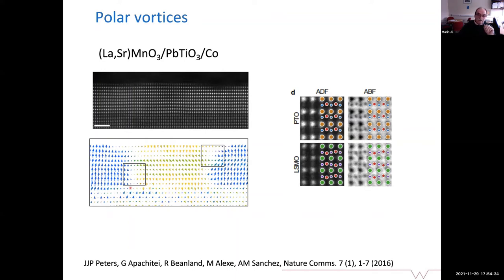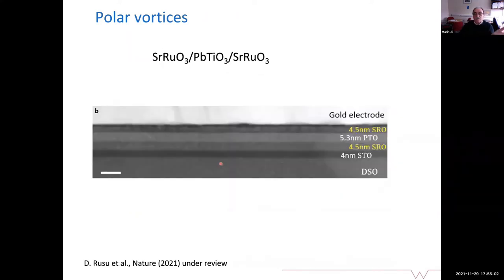But this swirling does occur usually at the domain wall, and it's again in pairs of positive and negative chirality. So there's a tendency for it to occur, but it's nothing as nice as in the case of lead titanate between strontium titanate layers. So what we did, we changed the metal. Again, we changed the metal with another metal. And not surprisingly, the metal is strontium ruthenate.